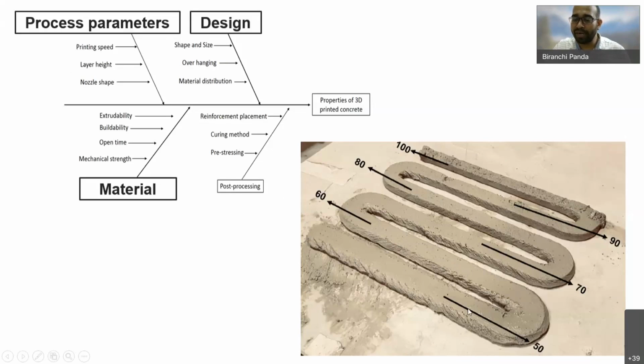So for example, if you want to print the material with different speed, it is very clear that without changing the flow rate, if you are changing the print speed, if you are going faster, the filament width is going to get smaller. And if you're going very slowly, material will be deposited more, so the width of the filament is going to be more. So always we have to deal with this kind of problem. So before we do printing, we have to optimize the relationship between the flow rate and printing speed. These have to be combined together, otherwise the filaments will look very ugly. Either there will be over deposition of material, or sometimes the filament will be very small. So this is how we deal with the printing speed and flow rate.